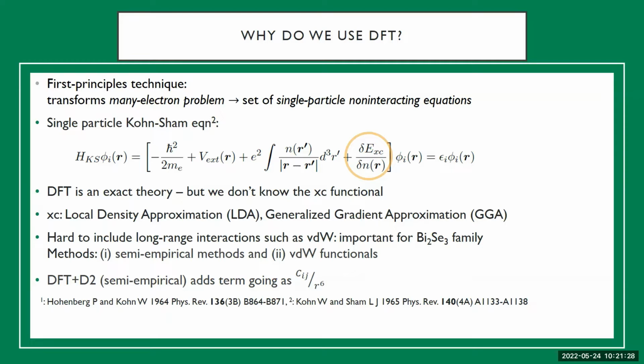So the one important thing to keep in mind is that while density functional theory itself is an exact theory, there is a term in that single particle equation which we don't know, which is the one circled, which is called the exchange correlation functional. And because we don't know it, we need to come up with some sort of approximation to it. Some of the common approximations include what's called the local density approximation and the generalized gradient approximation. In the LDA, they assume that this exchange correlation functional depends just on the electron density at a point. And in the GGA, it assumes that the functional depends on the electron density as well as its gradient, and so on. There are various approximations to it, but these are the 2 common ones.